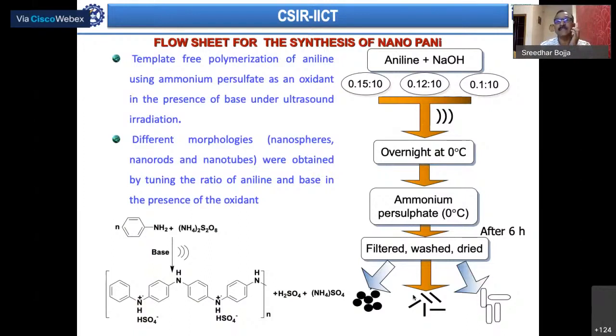For that, you have aniline and sodium hydroxide as the precursors. If you change their ratios and keep the synthetic protocol the same, you end up with these materials as spheres, rods, and tubes.